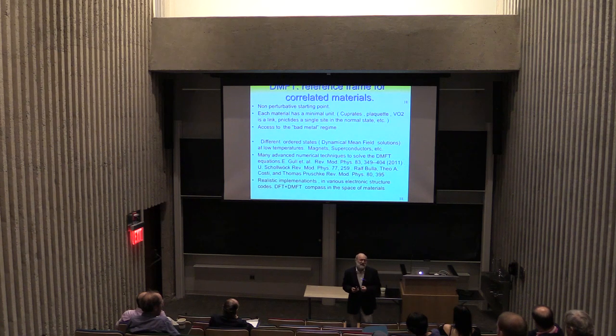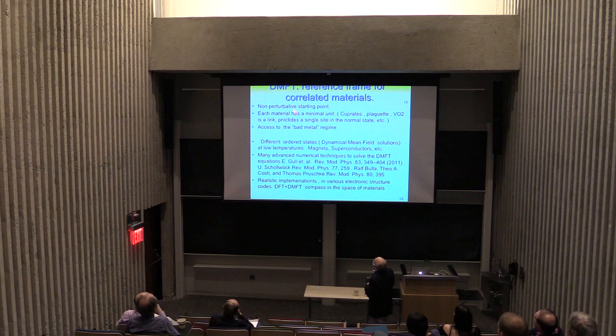However, there are extensions, and that's sort of what I wrote here. Each material has, in fact, a minimal unit that contains the local physics of the problem. Certain materials require two sites, some other materials require four sites. So what we're really doing for materials which require two sites or four sites is what's called a cluster extension of dynamical mean field theory, which is a generalization of the single site dynamical mean field theory to take into account some short range correlations.